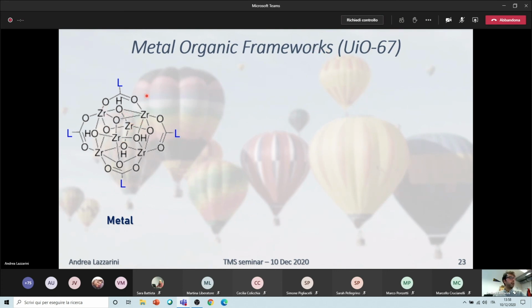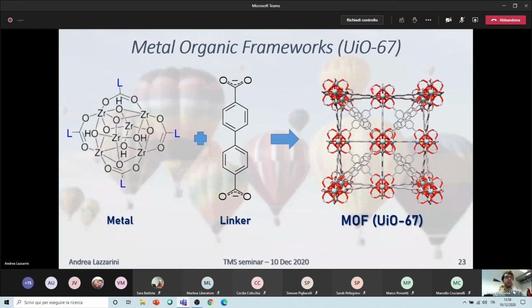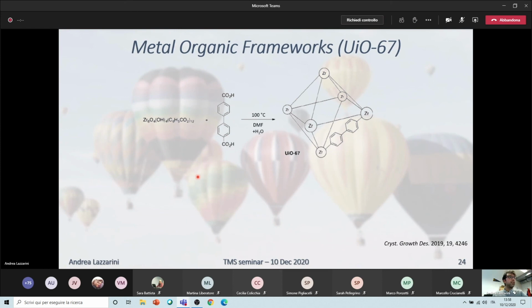So basically you have a zirconium metal node in which you have some linkers that are linking all the different nodes, and they are biphenyl rings with two carboxylate groups that are attaching to the zirconium node. And then when you couple them together, you can end up with a very ordered and extremely high surface structure. So classically, the UiO-67 framework is made just by pure biphenyl rings that are linking the zirconium nodes.